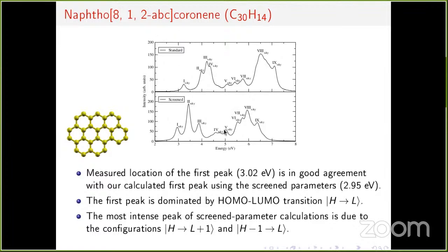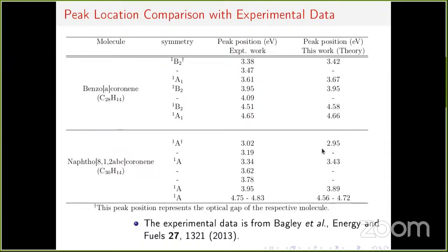Again, with screened parameters, as we saw earlier, we are getting very good agreement with the experiments. The first peak, being this one, which has a mixed polarization, is again dominated by a HOMO to LUMO transition. And the most intense peak for this case, which is the second peak, is also dominated by similar transitions as in the previous molecule, HOMO to LUMO+1 and HOMO-1 to LUMO. But we can do a better comparison for these two molecules for which experimental data is available.